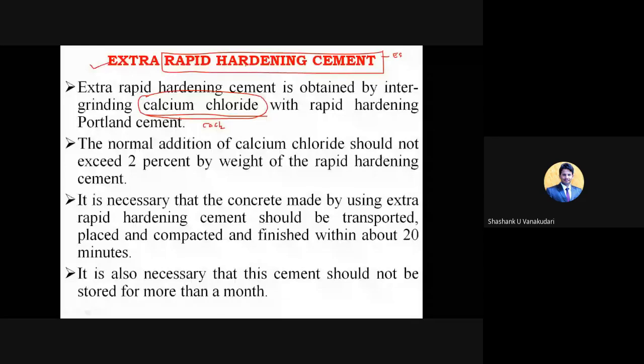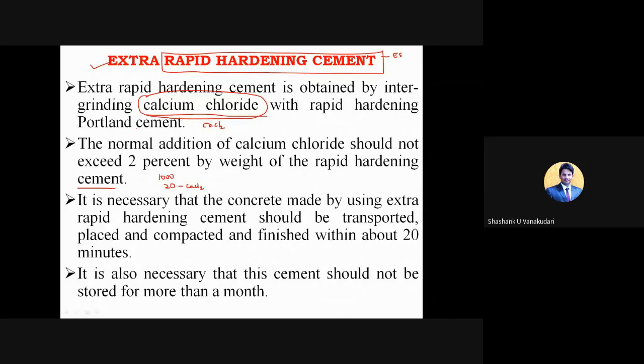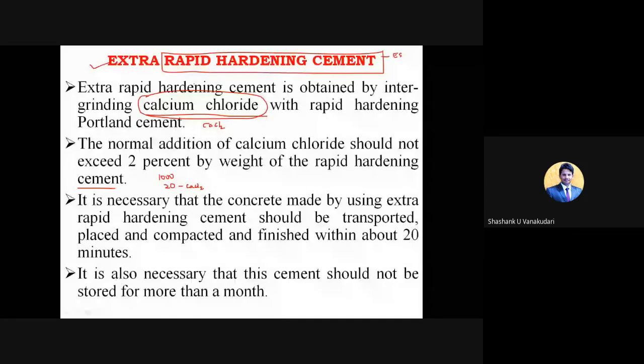Okay. The normal addition of calcium chloride should not exceed 2% by the weight of rapid hardening cement. Means for 1000 grams, you can use only 20 grams of this calcium chloride. Clear? So what is extra rapid hardening cement? Addition of calcium chloride to the rapid hardening cement is what we call extra rapid hardening cement. That addition of calcium chloride should not exceed 2% by the weight of rapid hardening cement.